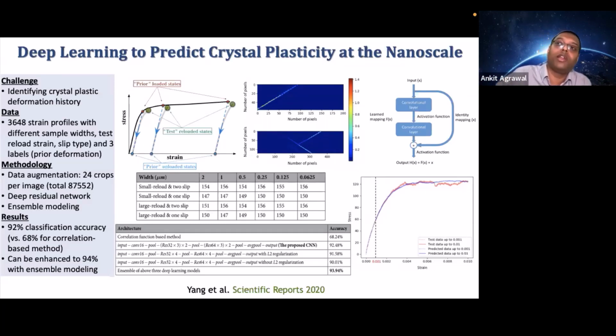Because if you buy a material from a manufacturing shop, how do you know whether this metal has not been in an accident in a car or something? Because just by looking at it, we won't know. So the way they do it is they apply a slight test load on this, so that this material goes to this green point, and then using that they can get these strain maps. And we believe that these strain maps have all the information that we need to identify what the prior deformation was.